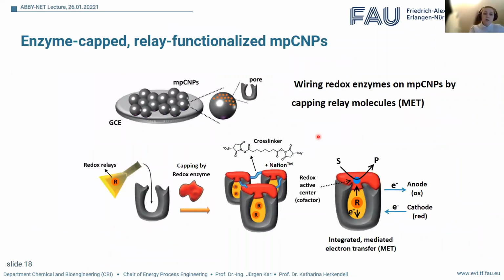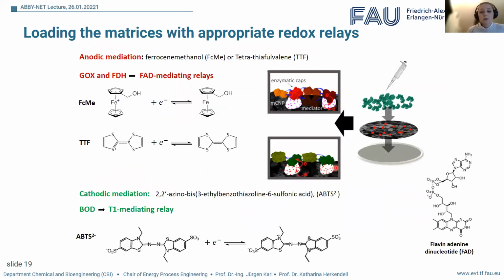What this would look like would be different protocols where we entrap the redox molecules and then cap the pores with the specific redox enzyme, which we then cross-link with different procedures, yielding very integrated, stable nanobiohybrid systems that could be used for biocatalysis over a prolonged time. Now, in this specific case, we found mediator molecules known for the specific enzymes that we wanted to utilize, which in this case were glucose oxidase and fructose dehydrogenase. We found two different mediators that were very successful to implement in the pores: one is ferrocene methanol and two is tetrathiafulvalene.